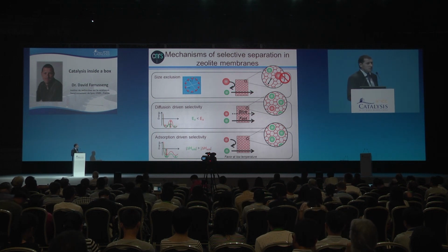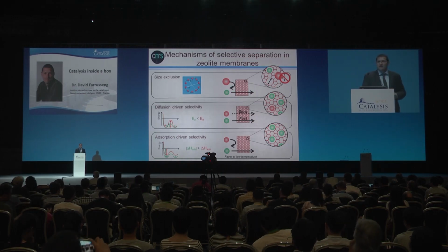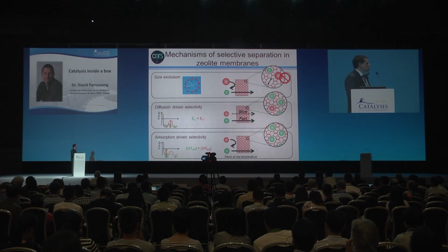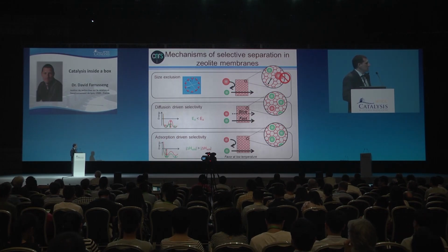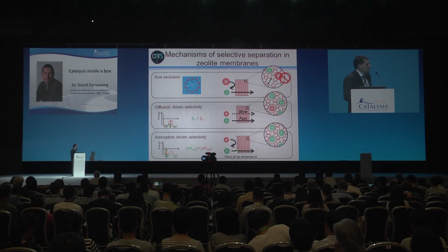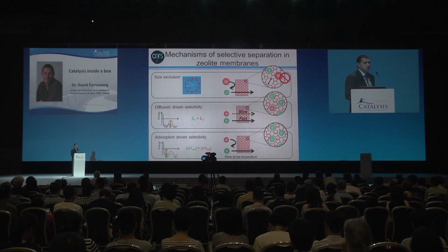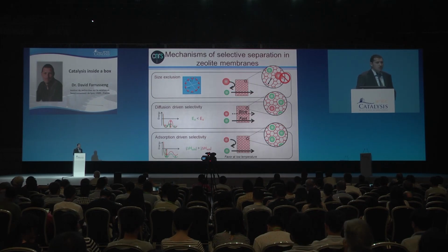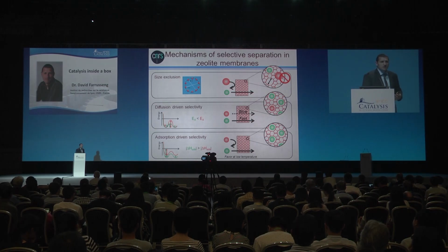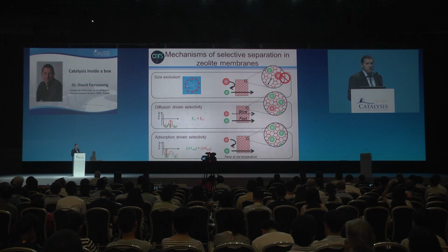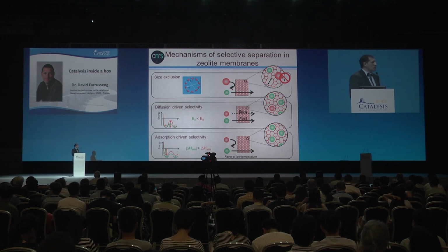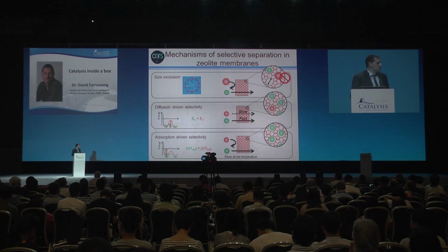The last mechanism known in membranes, but not so known actually in the field of catalysis, is what we call adsorption-driven selectivity. This is when, let's say, a substrate, the green one, has a much stronger adsorption energy than another one, and will, so to say, populate all the cavities, and they will not have room for the other component to adsorb and then diffuse. So it's also a size exclusion, and it is favored at either high pressure or low temperature. So I will show you here as well an example.